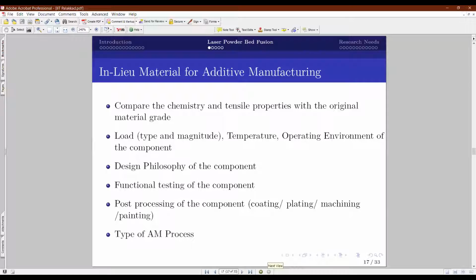Then the post processing, like coating, plating, machining, painting. See, most of the time what we understand, for example, we printed an aluminum turbine engine component a few years ago, and in place of A357, that is aluminum silicon, 7% silicon in it, when we did the anodizing, it failed on the 3D printed part. The reason is the presence of silicon disturbed my anodizing. This we came to know only at a later point of time, and within 4 to 5 months we fixed that problem. But the idea is whatever post processing we implement on the traditional process may not work on the 3D printed part. So there also we will face a challenge.